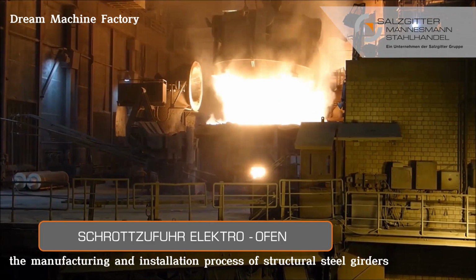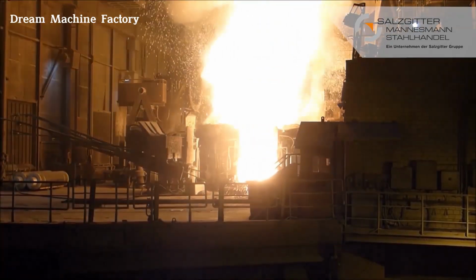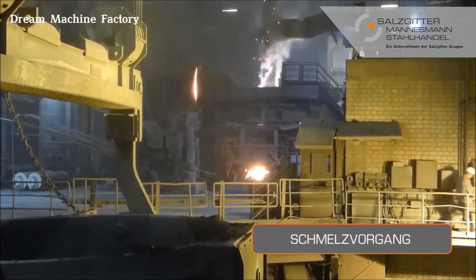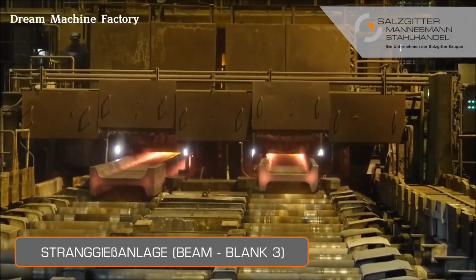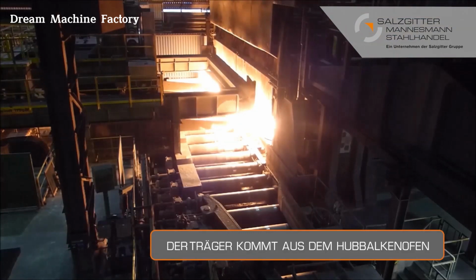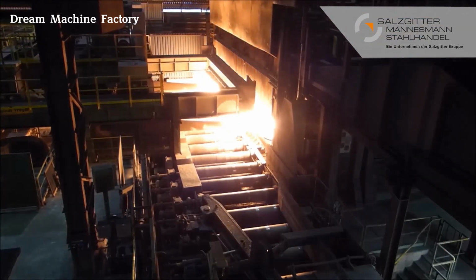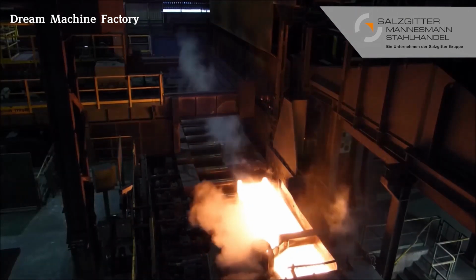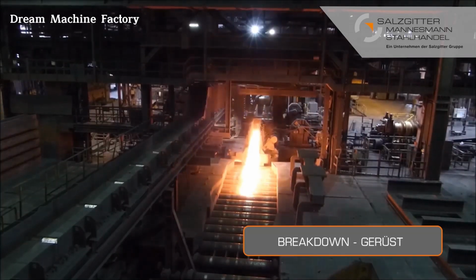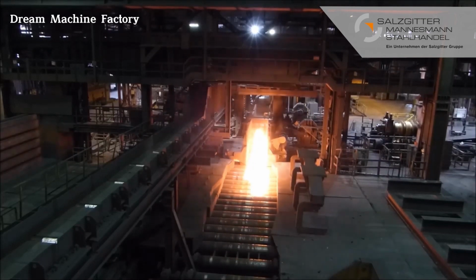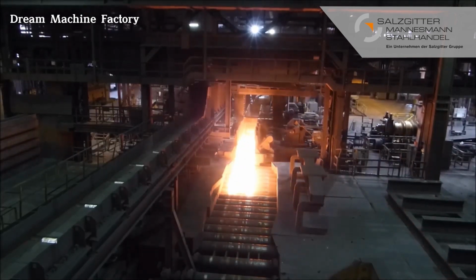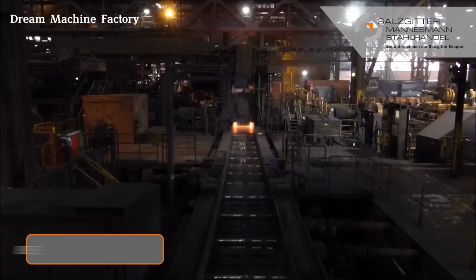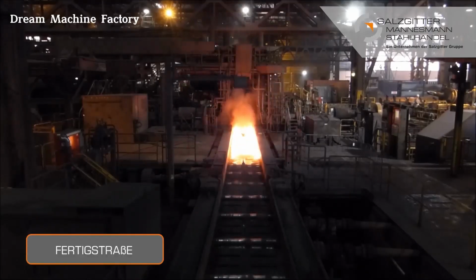Scrap steel is loaded into an electric arc furnace, where intense heat generated by high-voltage electrodes melts the material. Once molten, the steel is refined and poured into a continuous casting system, forming beam or slab-shaped billets. These are then reheated in a walking beam furnace for subsequent rolling into girders. The rolling mill breakdown stand reduces the reheated steel billets to the desired cross-sectional shape. Through a series of compressive passes, the girder's dimensions and mechanical properties are precisely controlled. Once the girders are formed, they are cut to the specified single lengths as per the project requirements.